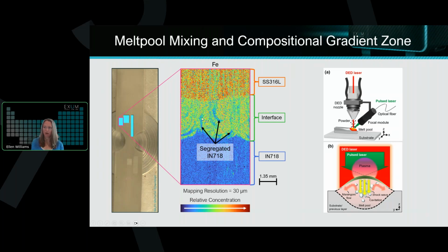And that's actually what we're able to see here, where we have those areas with relatively low iron. That is that Marangoni flow mixing, where we're getting some of that segregated nickel alloy within the iron as it's being deposited on the next layer. So really important defect to identify and to characterize and determine, are there some processes, are there some parameters that we could potentially change in order to minimize how many defects and impact the compositional gradient zone that we see here, in order to make sure that we don't create any sort of weak points at this multi-material interface.